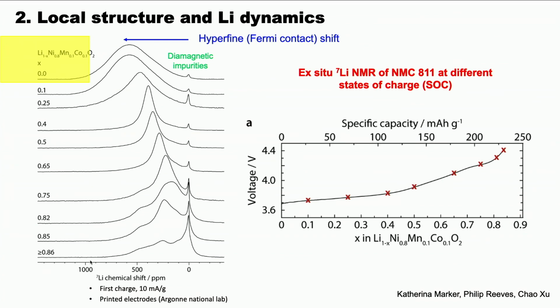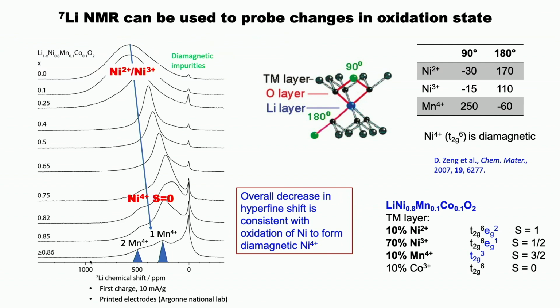And we do NMR of this material. And I've studied these materials, or me collectively and my group have studied them for many years, so we know how to interpret these quite complicated spectra. So we're going to do ex situ NMR. We're going to take different batteries at different states of charge and try and unpick what these broad blobs mean. And the main thing is that when you take this material, it's a mixed nickel 2+ to nickel 3+ oxide that gets oxidized to nickel 4+.